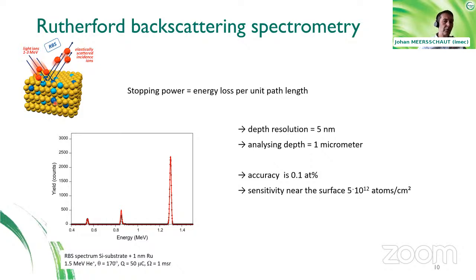And unlike photons, they are not absorbed, but simply lose kinetic energy. So when a particle penetrates, for example, a few nanometers deep inside a sample and is emitted, you will observe these particles as having a lower energy. And let's consider ions that are being emitted from within the silicon substrate. You see here that as you go deeper into the sample, you will have more and more energy loss. So in fact, you can probe the number of atoms in the sample as a function of depth.